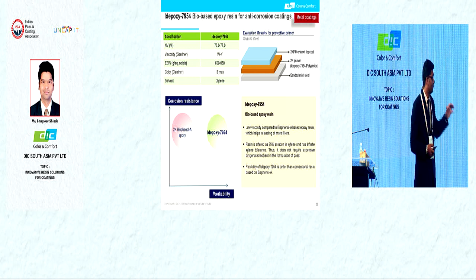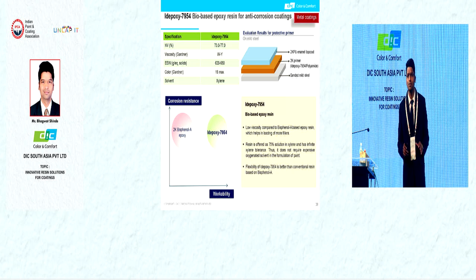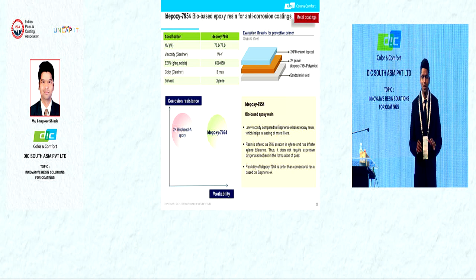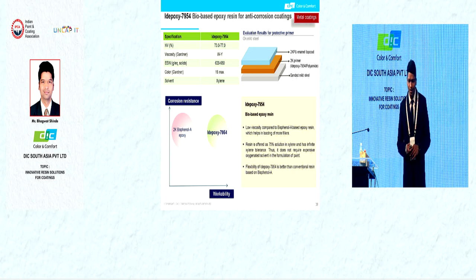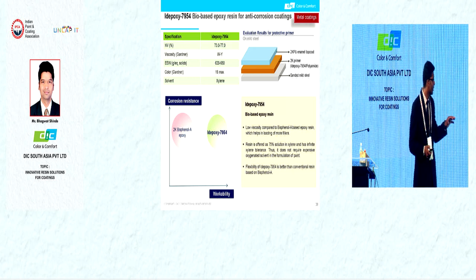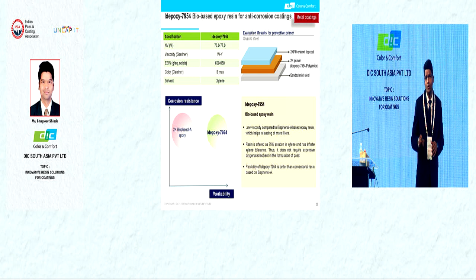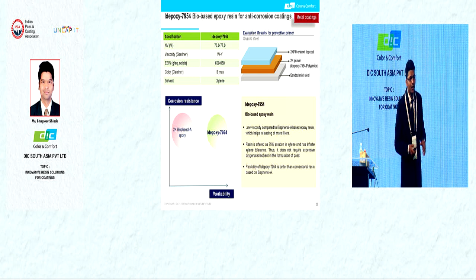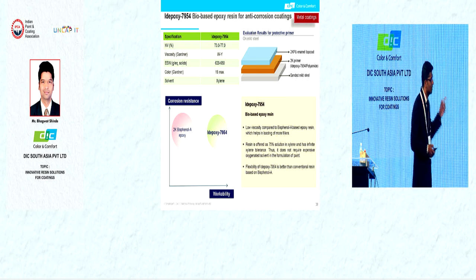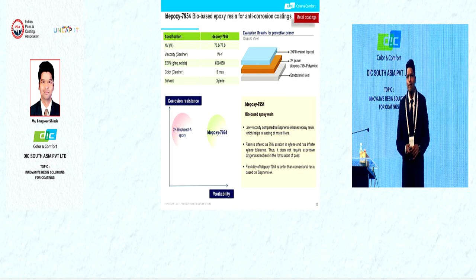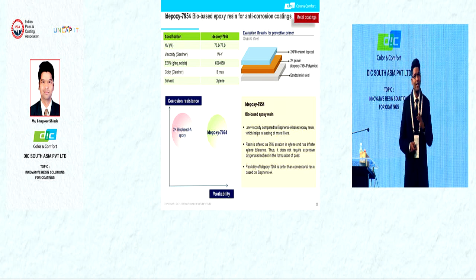So by using this product, there is no requirement of any polar solvent in your formulation. You can directly use only a solvent like xylene. So here you can reduce your formulation cost. Also, this product shows good flexibility, better than your conventional resin. The special property, one more, is the epoxy equivalent weight. This product has an epoxy equivalent weight higher than your conventional.